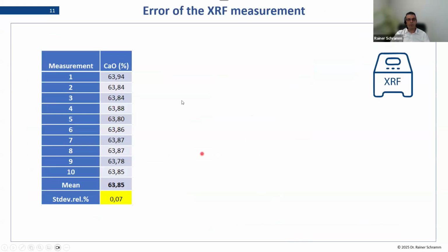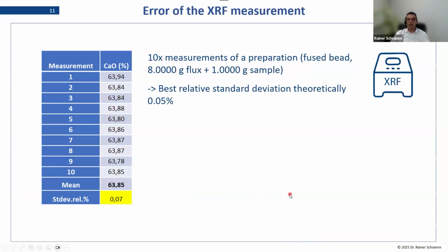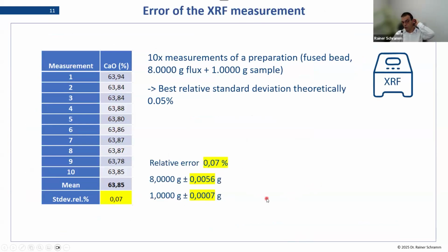So I took one glass bead and I measured it 10 times. And you see the standard error I get is 0.07%. And this means if I transfer this to my weights, for a 1 gram sample, this will be 0.7 milligram, or for the flux it is something around 5 to 6 milligram. So this is just so that we have a feeling of how much error it would be converted into weighing a sample.